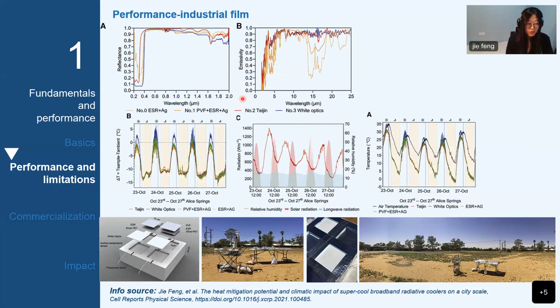In October 2020, we tested a group of polymers, either individually or combined with other layers. Matt just presented our results and I won't introduce in detail here. The result is that with peak solar radiation exceeding 1000 watts per square meter, the 4 groups of samples kept subambient surface temperature, up to 5 degrees cooler than the air even during peak hours.